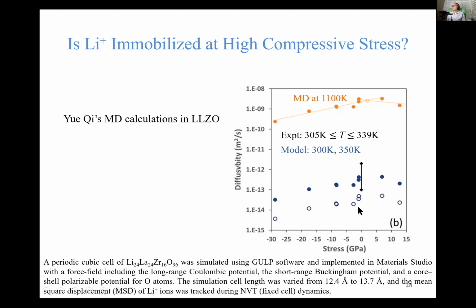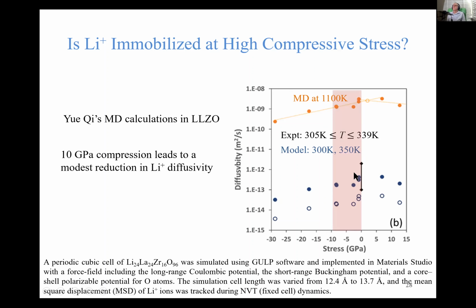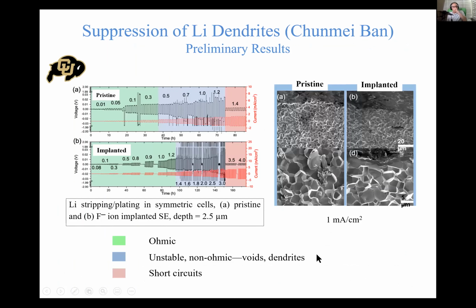And the experimental measurements of diffusivity are all done on this scale, right, at zero stress, and between 305 and 339 Kelvin. And as you can see, the prediction is quite accurate. The take-home message is that in the range where it's plausible compressive stresses, the compressive stresses lead to only a very modest reduction in the diffusivity of lithium. So this shouldn't be a showstopper. So the next step is to actually try it out and see if it works.